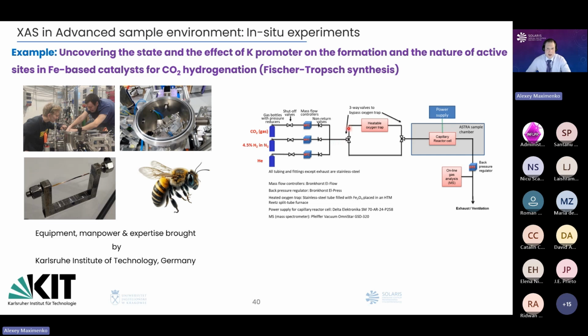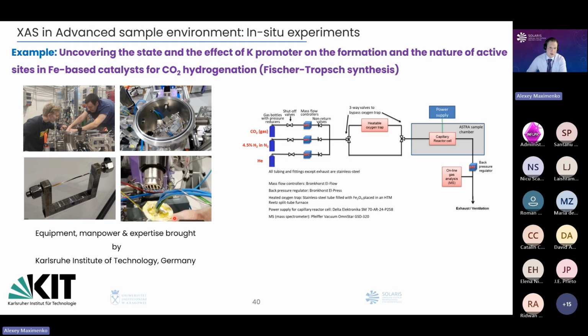And to give you a kind of joke about how experiments at synchrotrons are realized: this is an experiment which was realized at the beamline for which I am responsible. During the organization of this experiment, we found a leakage of the sample chamber, because we needed to make this experiment in vacuum. We tried different glues and different sealings, until we decided, okay, the last try, let's seal using beeswax. We did it on the beamline itself, we just sealed this feedthrough using beeswax. We succeeded, and you could see how nature could help us to provide such complicated measurements.